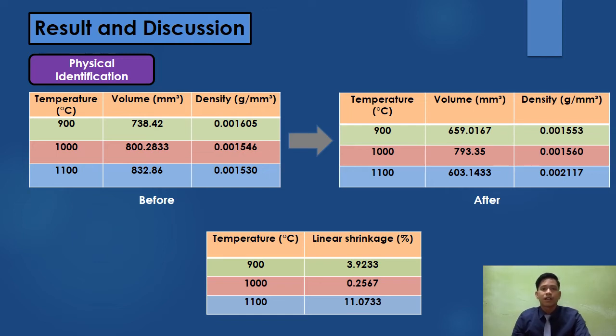This is because the degradation of porcelain calcite causes pores and capillaries to open, which generates vitrification and carbon dioxide emission. The viscous phase retains gas inside closed pores, decreasing sample density. The density was increased after sintering at 1000 and 1100 degrees Celsius because solid-state sintering bonds and densifies particles using heat below the material's melting point. Sintering reduces the compact's free surface area and increases density.